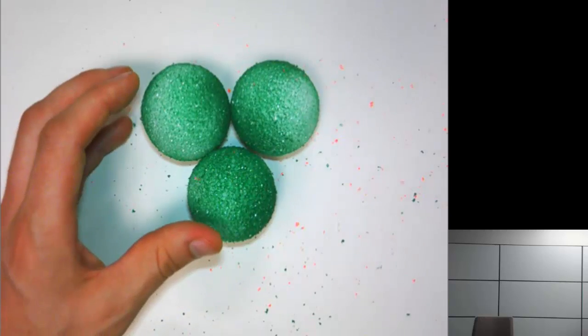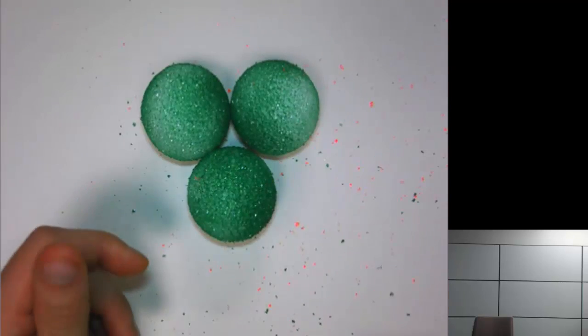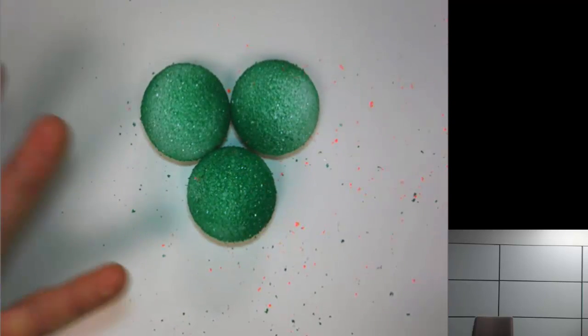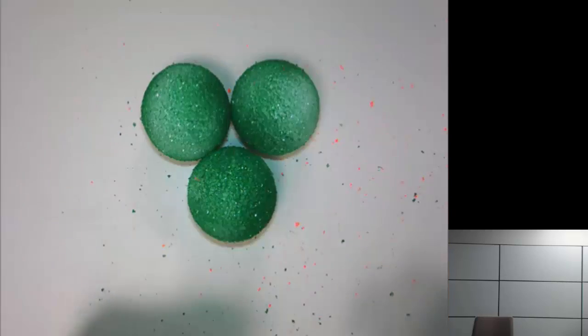And so you'll notice these sites got smaller and smaller as I went from having many atoms around it to having just a few atoms around it. So the cubic sites are the largest and then the octahedrons, then the tetrahedrons, then triangular sites.